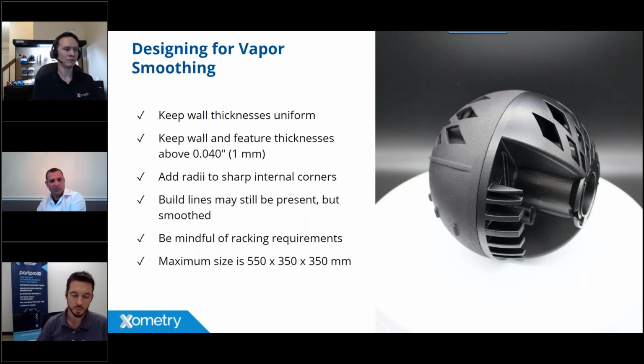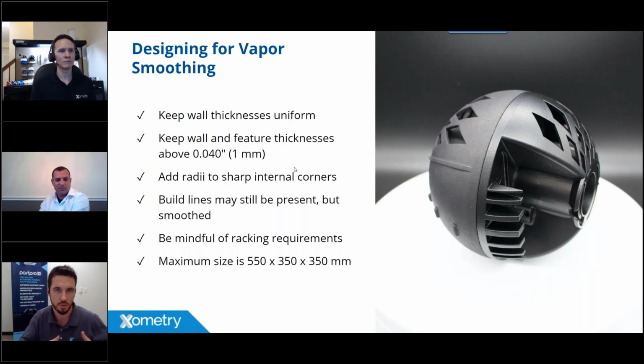Absolutely. Luckily with 3D printing, you have a lot of freedoms to design. That's the benefit of this industry, right? And if we can start solidifying what those limits would be for vapor smoothing, making an equal wall thickness throughout the part is a big benefit, because it is a thermodynamic process. That carefully controlled environment I talked about in the beginning is all to ensure condensation on the part. And if there's a variation in thickness, you can see a variation of processing simply because this vapor wants to get back into a liquid state.